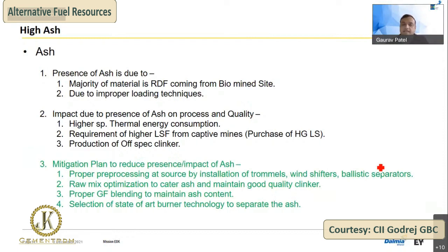Proper green fuel blending: if we have a variety of green fuel AFRs available at our site, we should mix properly to have at least 1 or 2 days of feeding heap available, so that there won't be fluctuation in ash, moisture, CV, and we maintain process stability. And selection of state-of-the-art burner technology to separate the ash, so that only the flame, only the heat, goes into the system and the ash is separated through that burner.